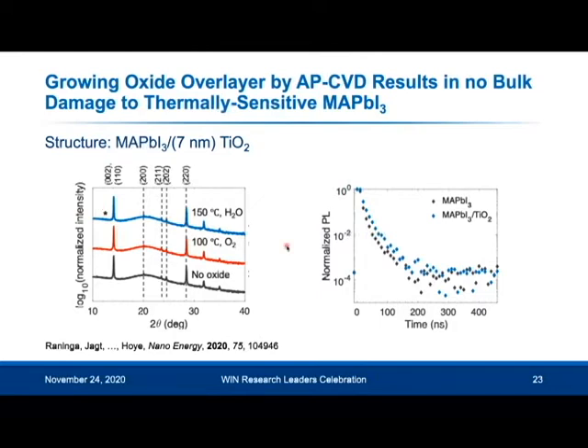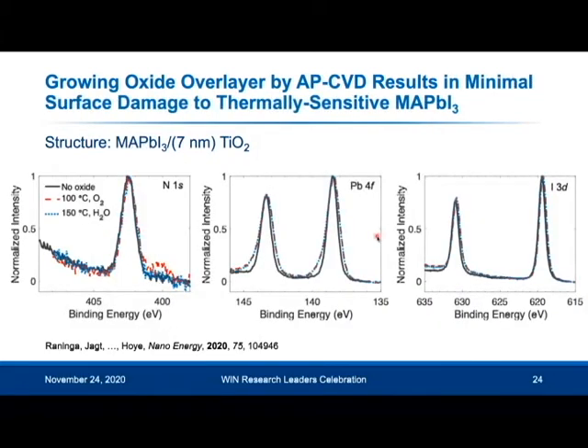And we also look at the time resolved PL, and we found that after the growth of the TiO2, we have also avoided decreasing the PL lifetime, which shows us that we're not introducing any extra non-radiative recombination channels. So now we know the bulk remains the same, but what happens at the surface?